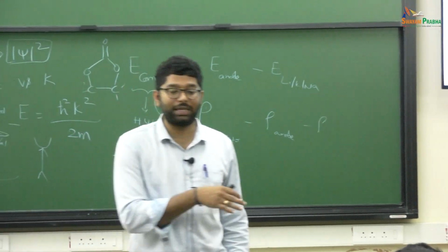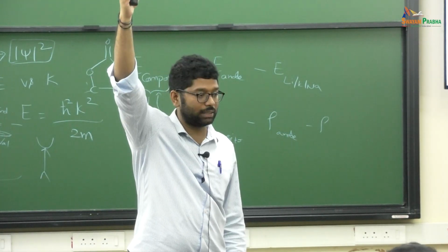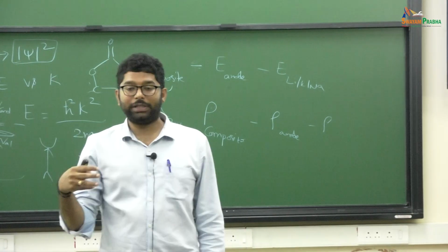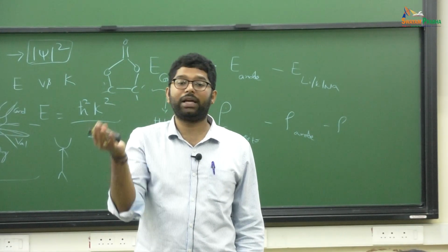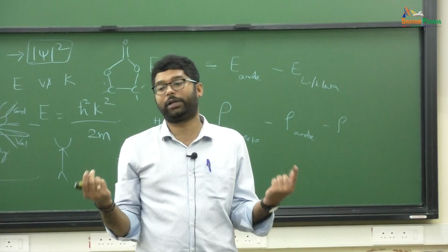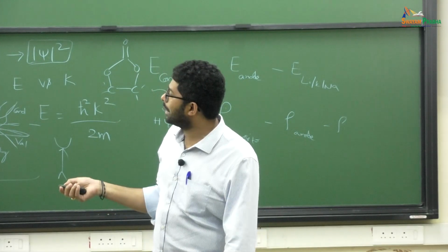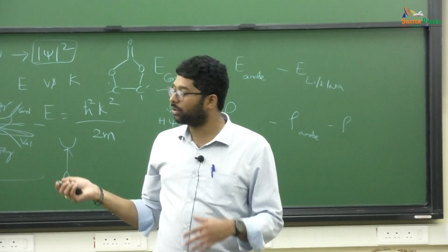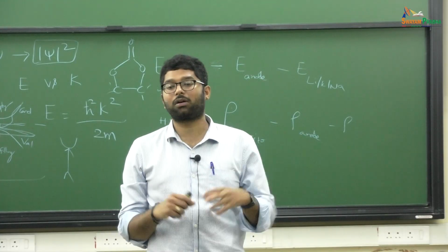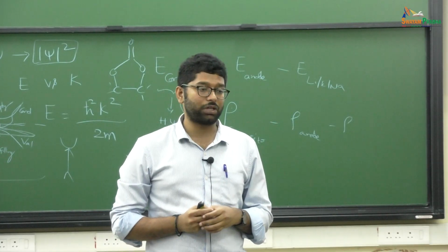This is one thing. So we said that we can load up to 5 layers in the case of lithium on these materials, and we can load up to 4 layers for the sodium, but only 1 layer of potassium was done. So in order to understand that, we have plotted these, similar to the plots that I have shown you in the beginning.